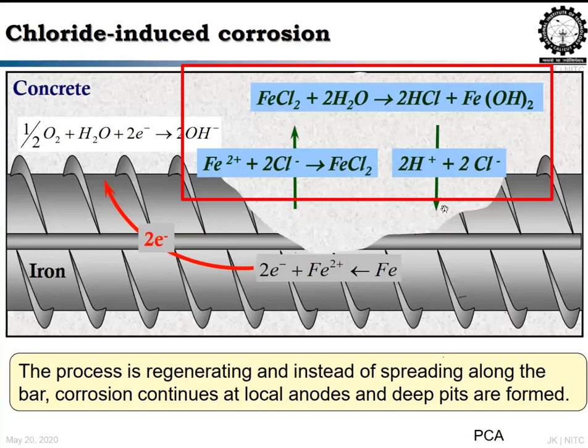This HCl, because of the reaction, will further break into hydrogen ions, causing hydrogen embrittlement, and again the chloride will be there. Again the same chloride will react with Fe2+ ions and form ferric chloride. This cycle will keep on continuing throughout the life of a structure once the corrosion is initiated. So we call it a regenerating process. So we should be very careful about this chloride-induced corrosion.